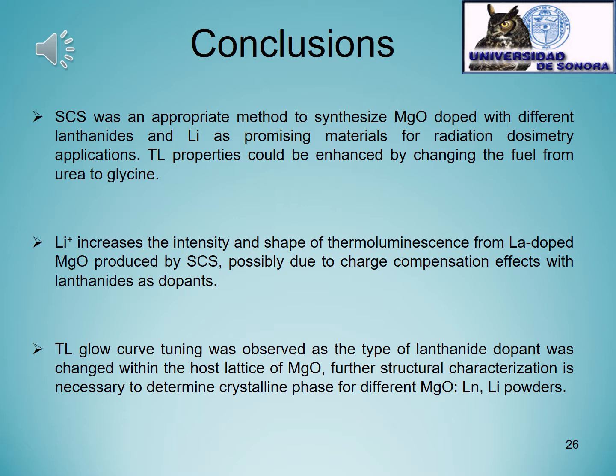We can say that TL properties could be enhanced by changing the fuel from urea to glycine, in terms of peak positions, in terms of linearity range on the dose response curve, and also an improvement on the TL fading in terms of storage times, which was increased significantly.